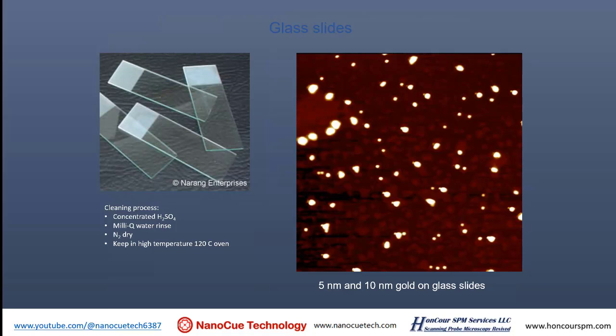That's because you don't know whether what you look at is nanoparticle or particles already on the glass slide. That's because a glass slide is glass, it's amorphous, and there's no fixed crystal structure. So whatever shows up there, it's there. There's no guarantee. So you have to image when it is blank, and if it is free of the things you're looking at, then you can use this as the substrate.